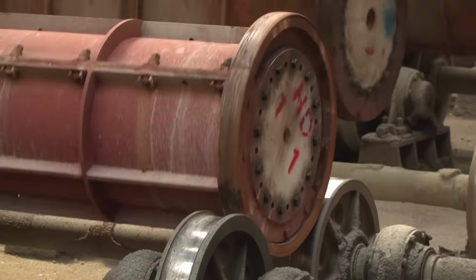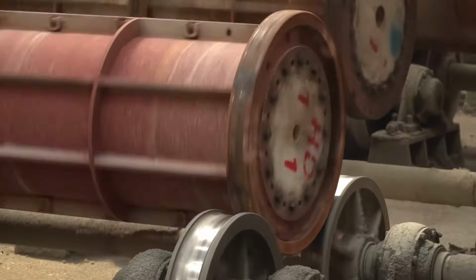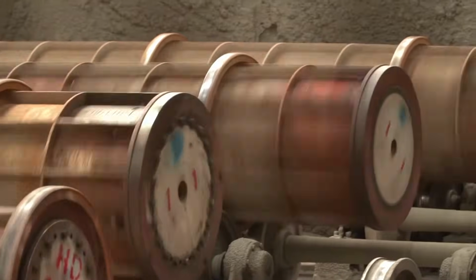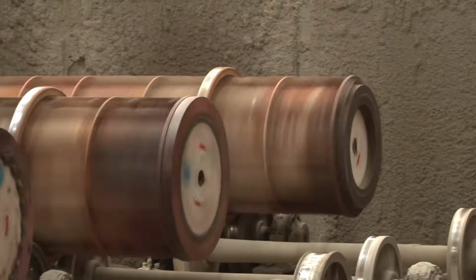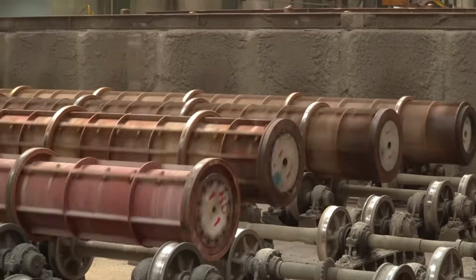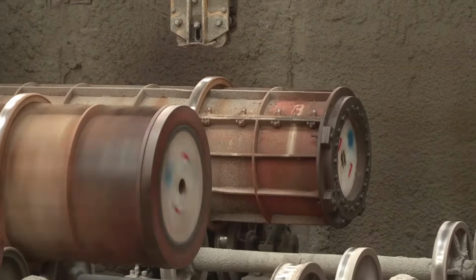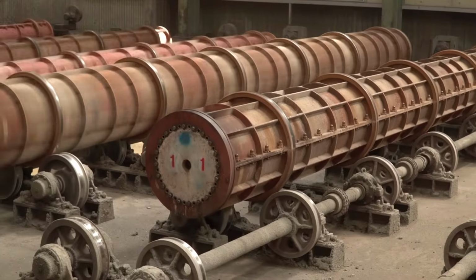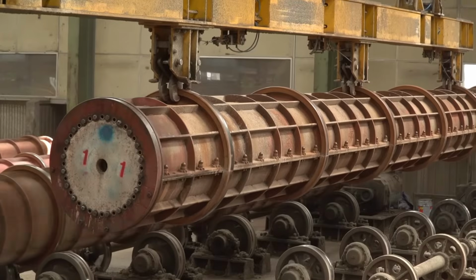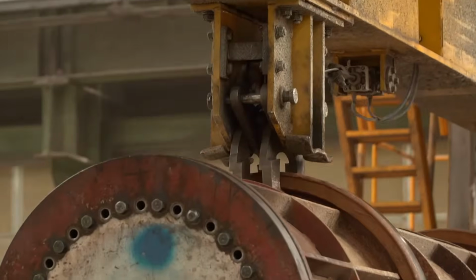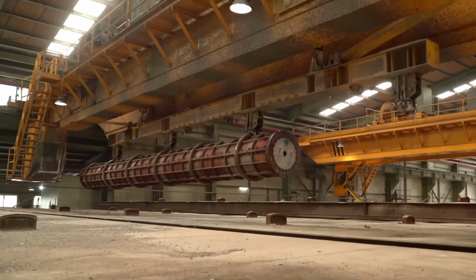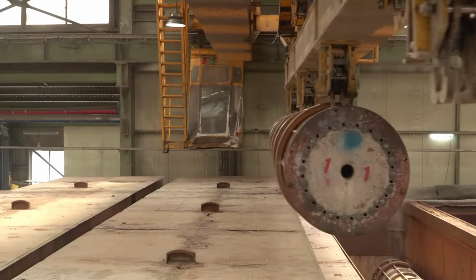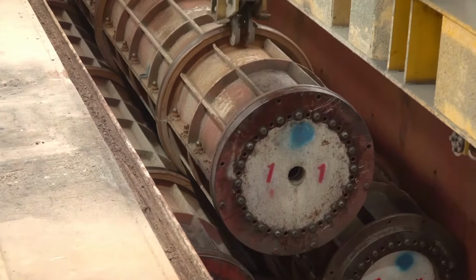That dense outer layer is what allows PHC piles to resist corrosion, water intrusion, and underground chemical attack, even after decades of use. For several minutes, the mold spins at high RPM, the concrete inside transforming under pressure and motion. Then, the rotation slows, the mold is released, and it's wheeled out to the curing area, ready for the next transformation.